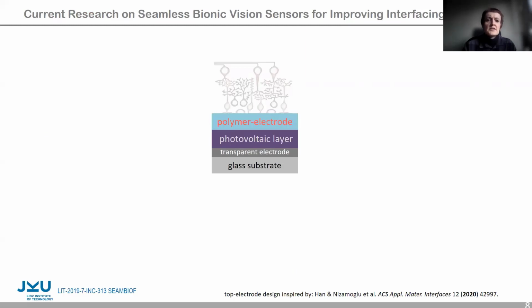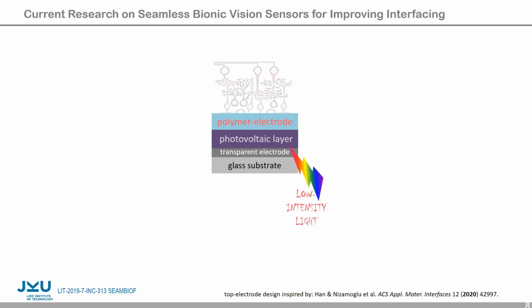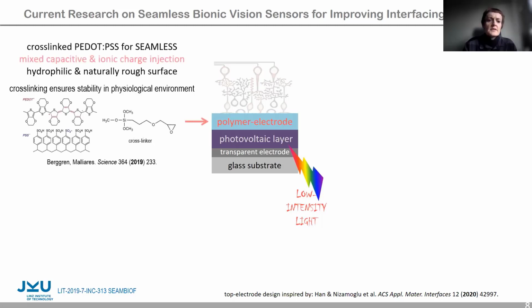The present strategy to obtain a better stimulus transduction from the photovoltaic layer is to reduce the required intensity of illumination. For this, we utilize a polymer electrode consisting of the conductive polymer blend PEDOT:PSS, which is chemically cross-linked for stability in the wet physiological environment.